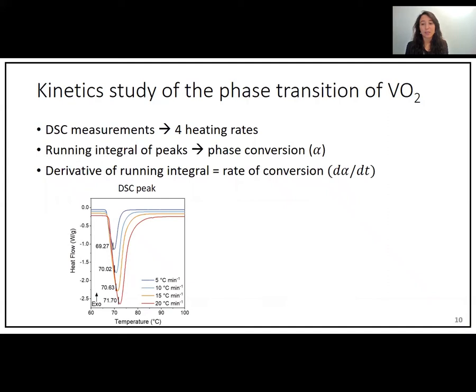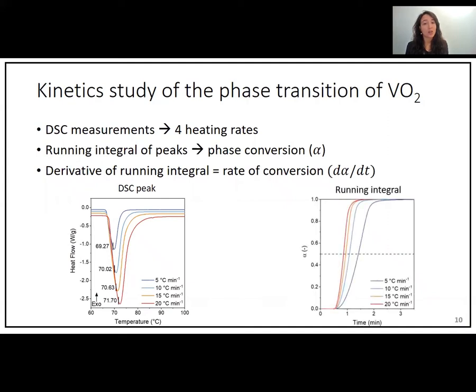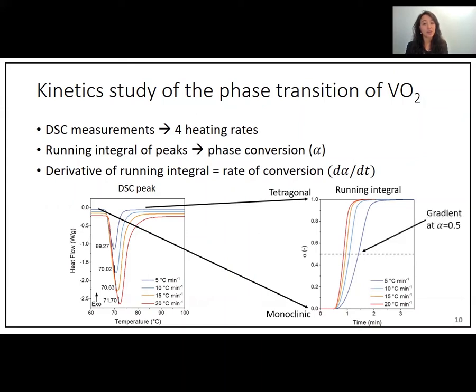The peak area with respect to time corresponds to the running integral of the peak. This is the conversion of VO2 from monoclinic to tetragonal. Therefore, below 60 degrees, when VO2 is monoclinic, the conversion is 0, while above 80 degrees, this value is 1. For the kinetic study, the gradient at the 50% conversion is very important, as this gives the rate of conversion of the VO2 monoclinic to tetragonal. Additionally, the corresponding temperature when alpha is 0.5 is also required.